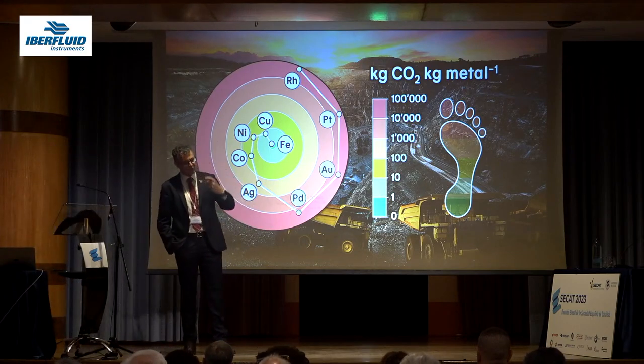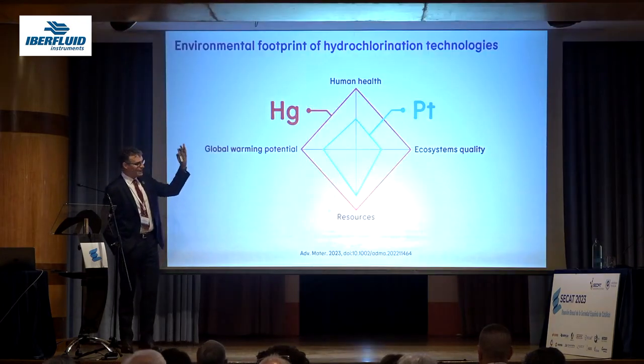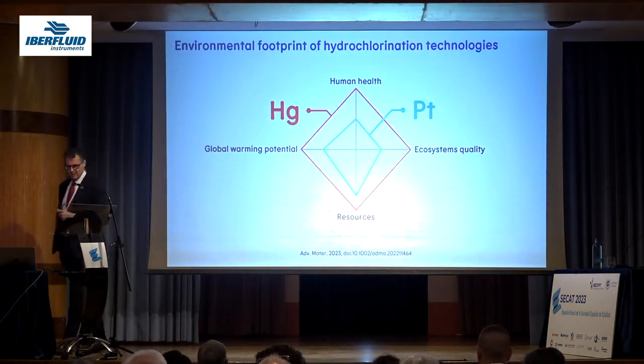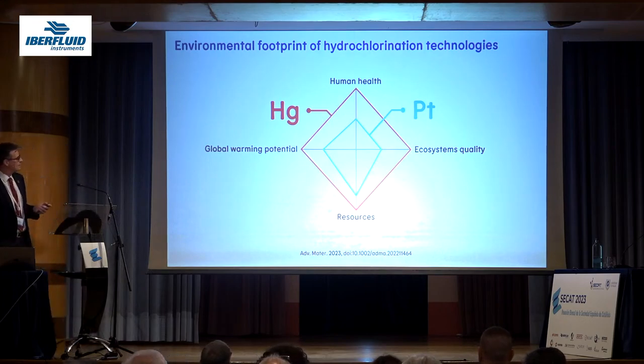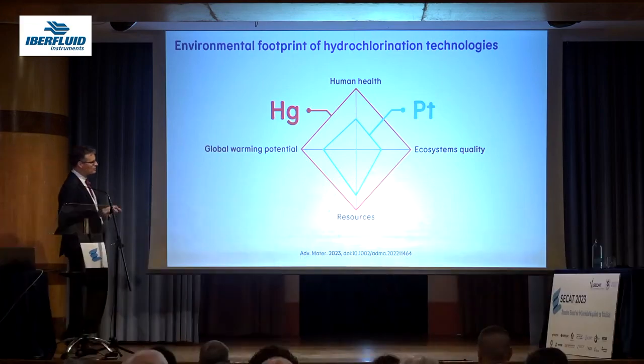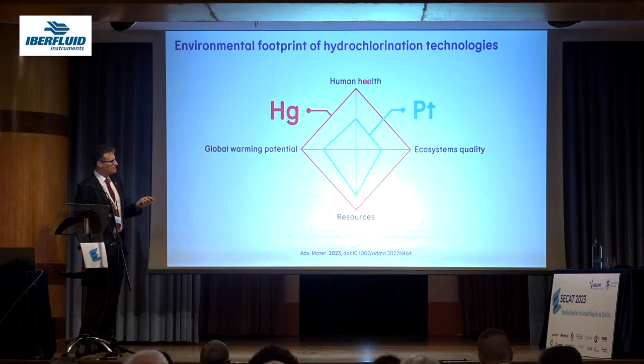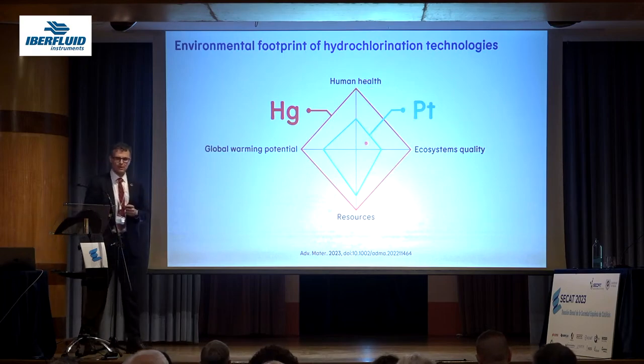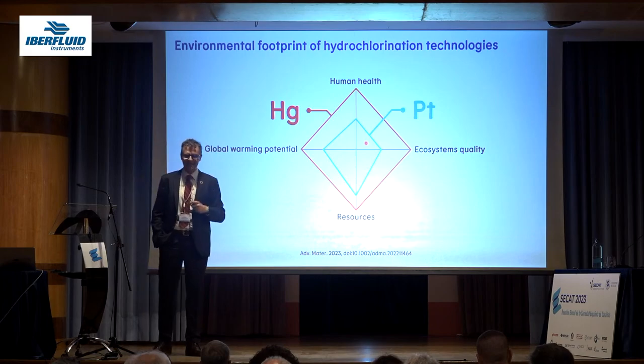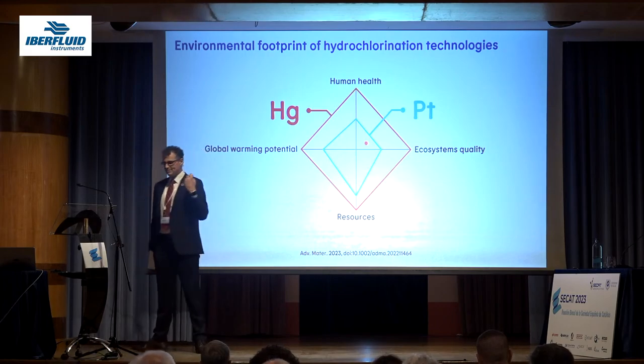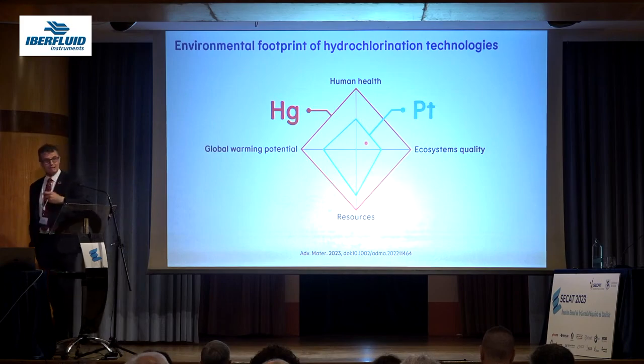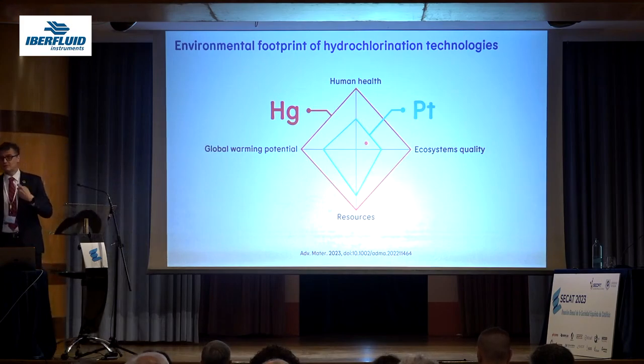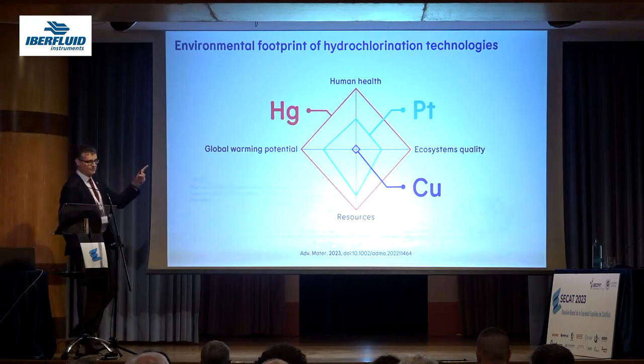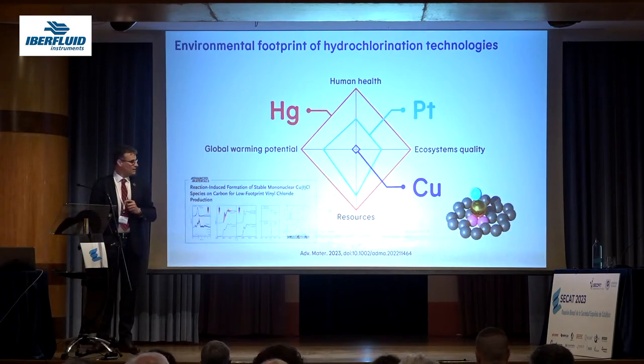One step further, not mercury, because if you look at LCA indicators, and these are typical indicators coming from life cycle analysis, human health, ecosystems quality, resources, and global warming potential, we could see that the platinum technology has a much lower footprint compared to the mercury. But that's obvious, right? Mercury is extremely toxic, right? So it's better, but is this what we need to aim at if we have the possibility to do something better? Actually, if we shift to copper-based catalyst, you will have a footprint that is almost 0,